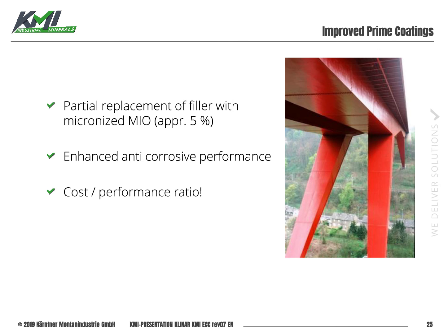Another application is a simple way to improve existing prime coatings simply by replacing a small amount of the filler with micronized MIO. Here we speak about 5% per mass up to maximum 10% per mass. It's an easy way to improve the anti-corrosive performance simply because you do not have to change your formulation around. So you can work with the same active pigment package, you can work with the same additives. There is just a slight influence on the color if you replace a white filler with a dark gray micaceous iron oxide. But here we speak about a prime coat and there shouldn't be a big issue with that.